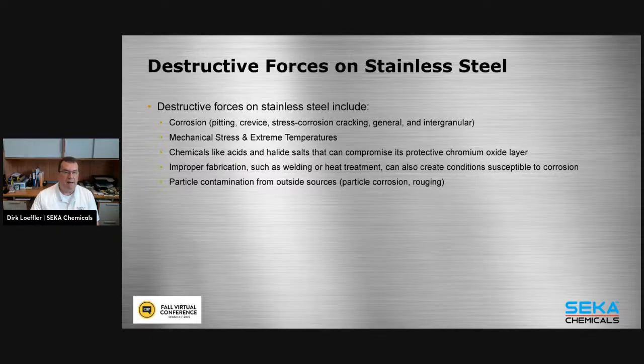And then we also have, kind of rare, but I've come across it a few times, particle contamination from outside sources. For example, we were working with a company installing a brew house outside, and people were welding above the brew house. As you know, when you weld, there are always sparks flying around, which are actually small pieces of metal. They ended up on the stainless steel surfaces and then caused damage from there. So that is what we call particle contamination.